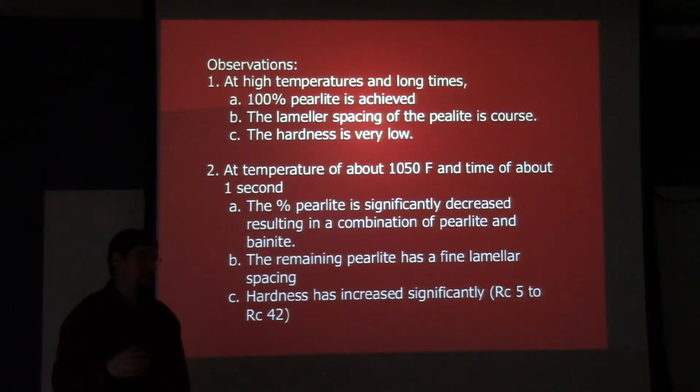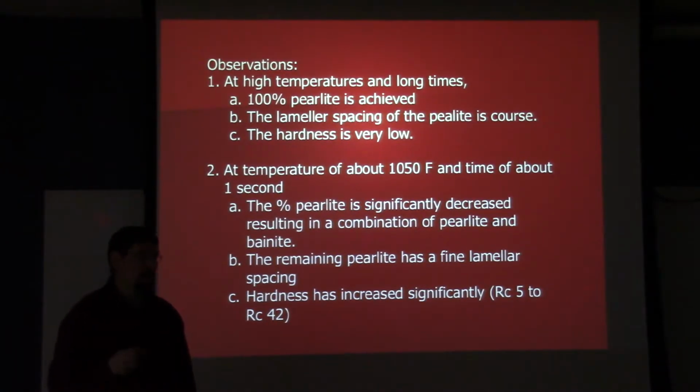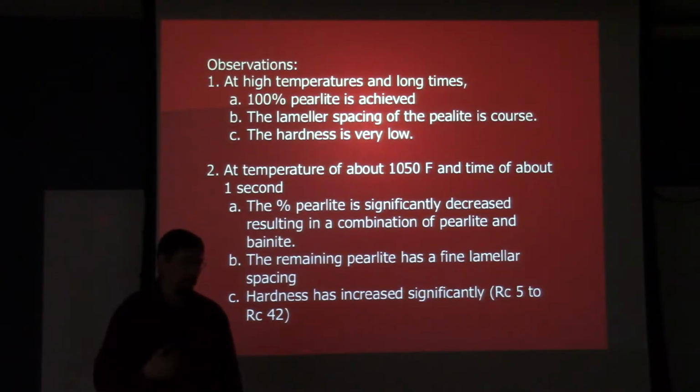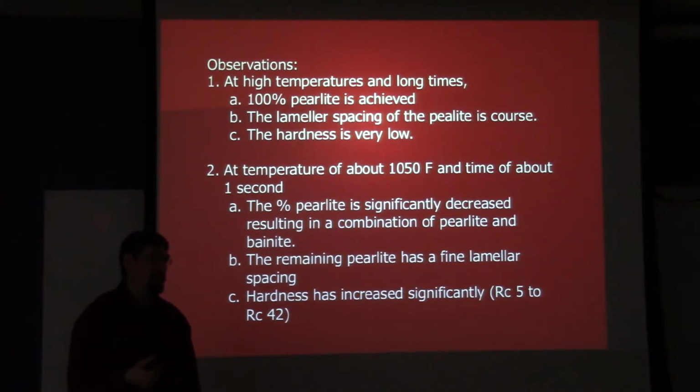Bainites can be very tough, but they can also be very detrimental and cause a lot of loss in toughness. When you have just a small amount of bainite embedded in a matrix of pearlite, or pearlite and blocky ferrite, that bainite will be the hardest constituent in there, but if it's isolated all by itself, that hard spot's going to serve as a crack initiation site.